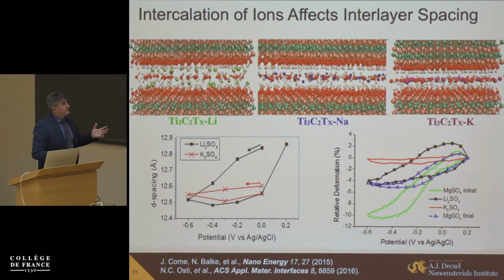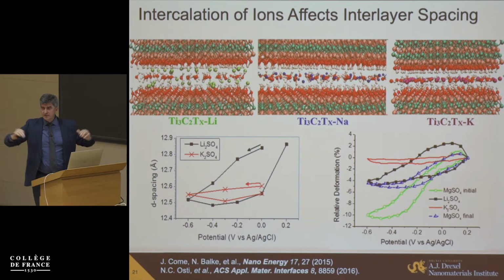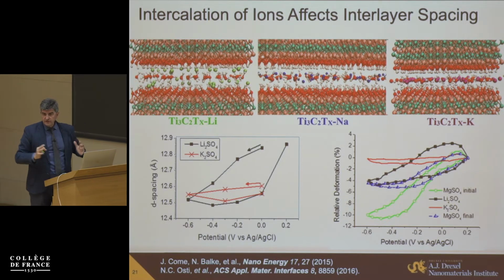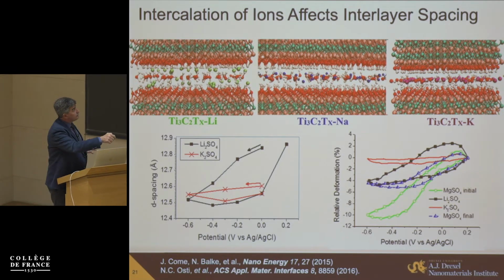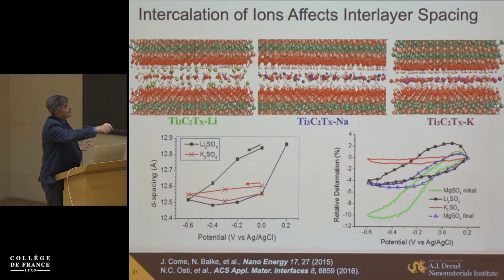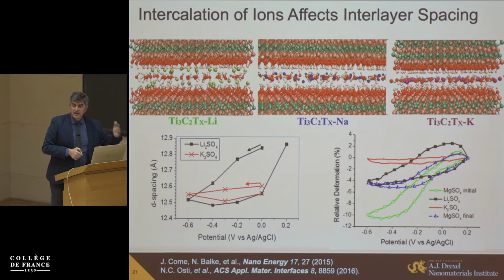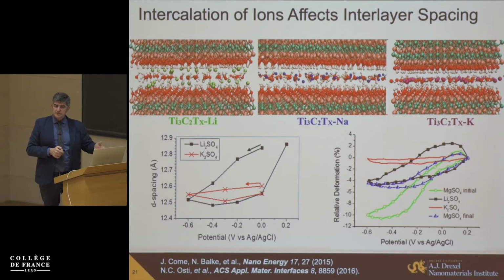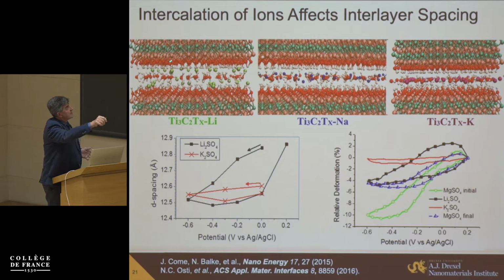So what happens when we take these two-dimensional flakes assembled into a film and start charging here? First, pretty much we always have ions between the layers. Even from the moment of synthesis delamination, when we use lithium or tetrabutyl ammonium, tetramethyl ammonium ions, we get ions and eventually solvent like water in between, unless you heat it up to a couple of 100 degrees C and dry it completely here. And different ions will give you different behaviors, and actually when you start intercalating into this